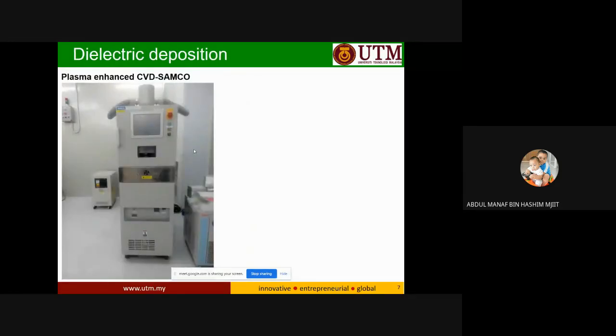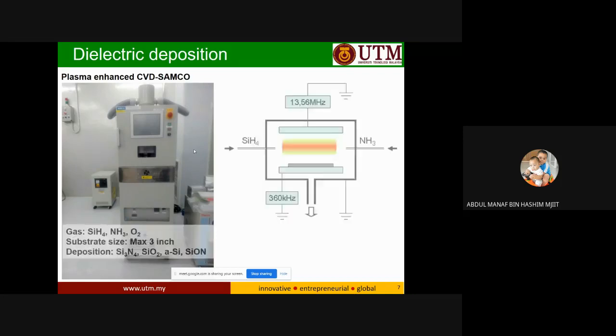Also, we have equipment for dielectric deposition. We have plasma CVD, PECVD. The gases that we have now are silane, ammonia, and also oxygen. So meaning that you can deposit silicon nitride, silicon dioxide, amorphous silicon, and also silicon oxynitride. The maximum size of a sample is up to 3 inches.